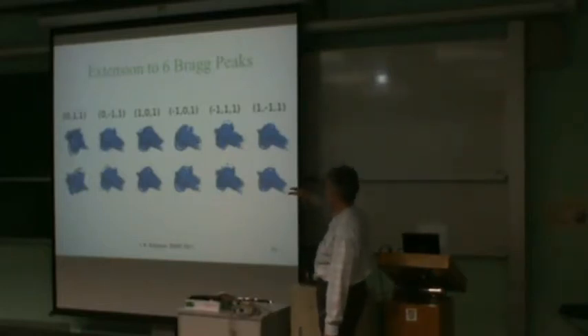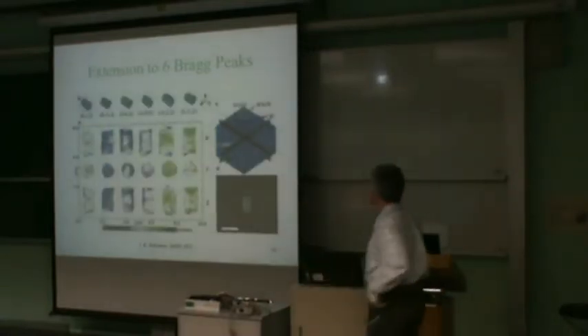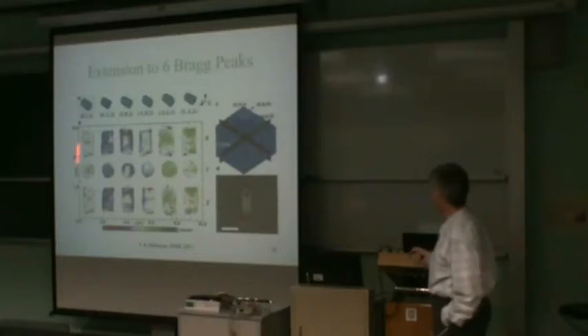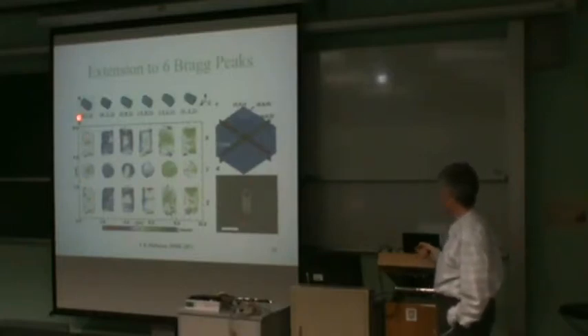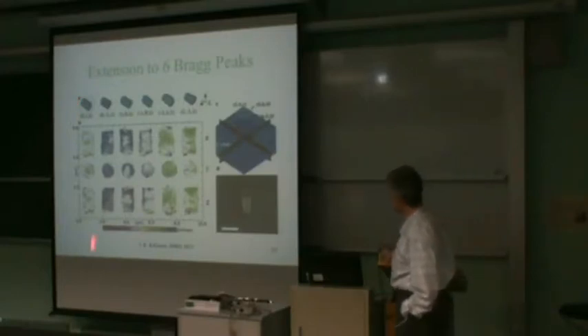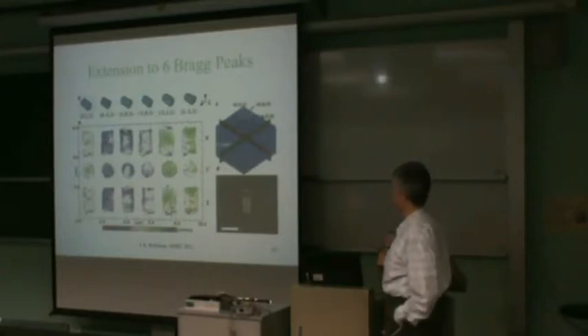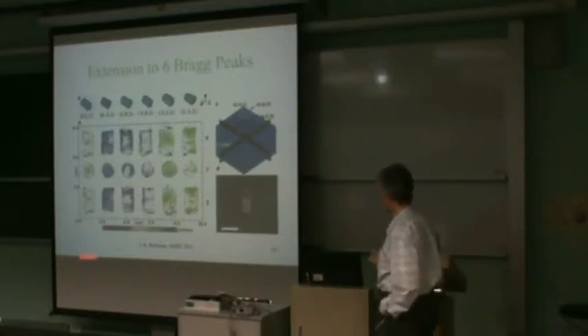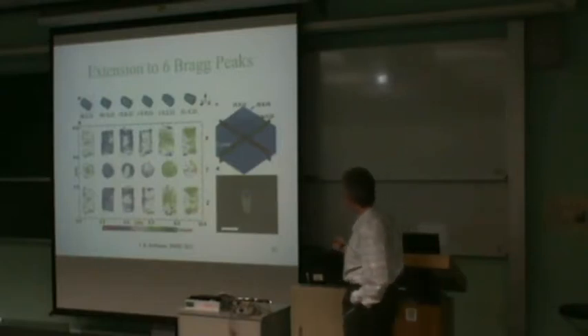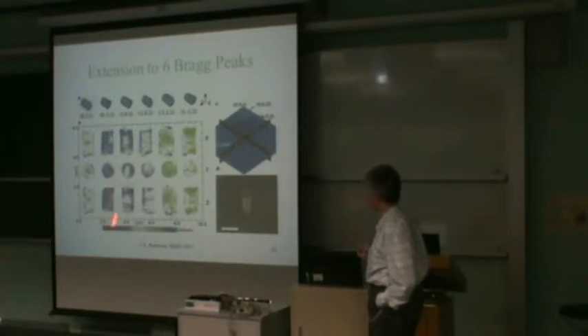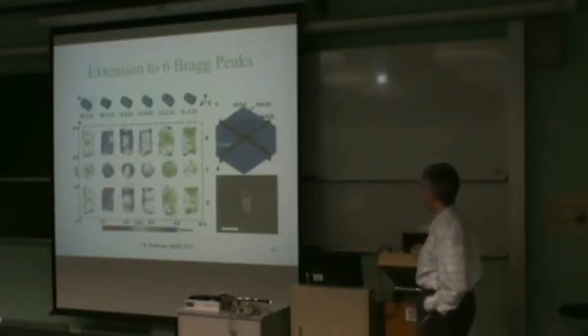Obviously, we're seeing the same Fourier transform of the shape, and so most of the information in the diffraction pattern looks the same, but the small differences come from the fact that the strains are not identical. So these show X, Y, Z cross sections through the image. These are now images of the 6 different Bragg peaks, imaged separately by the inversion method that we use, and these are cross-sectional images of the pattern of strain inside, using unfortunately a different color scheme from the one I used before. And you can see that there is quite a rich distribution of strain inside there.